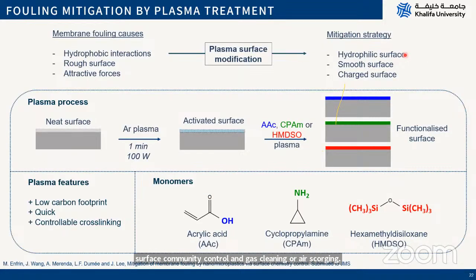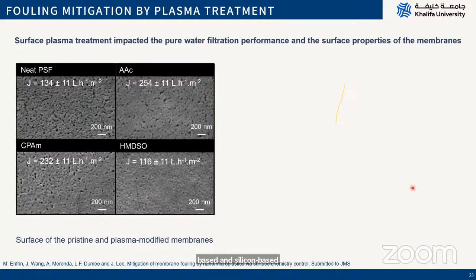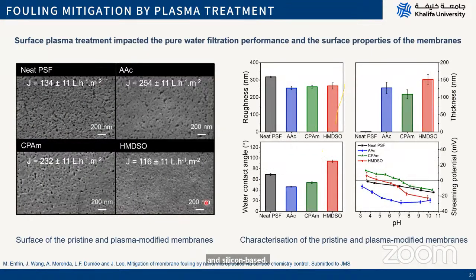There are a number of solutions in terms of membrane modifications, and we selected three monomers to be able to fine-tune the charge of the membrane eventually, looking at acrylic acid-based, amine-based, and silicone-based polymers. We did some trials to optimize the system. I will not go into all the details there, but let's just say we could generate composite membranes with different thicknesses of each polymer to have the same nominal flux and very, very close surface roughness and morphology.